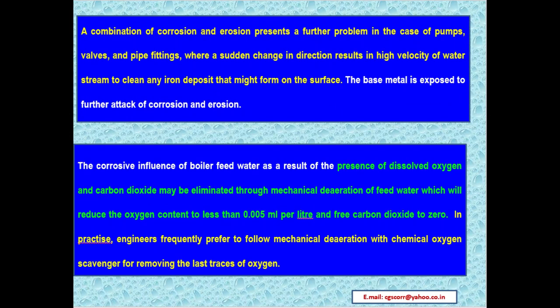A combination of corrosion and erosion presents a further problem in the case of pumps, valves, and pipe fittings, where a sudden change in direction results in a high velocity water stream that cleans any iron deposit that might form on the surface. The base metal is exposed to further attack of corrosion and erosion.